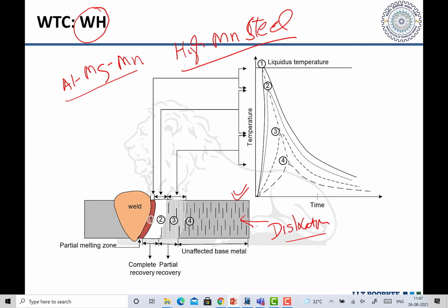And you notice the different zones will be experiencing different temperatures. Say take points 4, 3, 2 and 1. What kind of peak temperature will they be experiencing? Point 4 very low, point 3 a little high, point 2 further high, and point 1 is maximum, in the vicinity of the weld nugget or the joint interface. So the peak temperature is high, and you will notice that the recovery will take place significantly and in a very short time. So the complete recovery you will be noticing here, not just recovery, but formation of newer grains, even coarser grains.